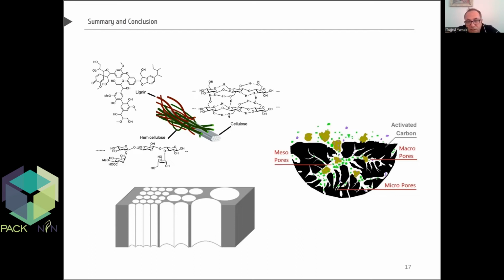Some of the biomass-derived activated carbons with excellent capacitive performance are obtained from low carbon yield precursors, which in turn sustainably limit their large-scale production. Maybe the major carbon contributors such as lignin, cellulose, or hemicellulose can be extracted from the precursors and then purified and concentrated prior to carbonization to achieve a high carbon yield.